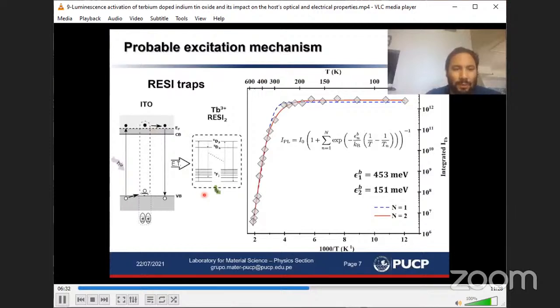So after excitation and the formation of an electron-hole pair, the electron-hole pair will form an exciton bound to a rare earth or rare earth cluster, because these rare earths can form clusters of 2, 3, or higher sizes. These clusters will create a potential that will attract holes or excitons, and they will be bound to this potential. After recombination, or the annihilation of this exciton, energy will be transferred to the rare earth, and therefore the rare earth is excited to a higher level.